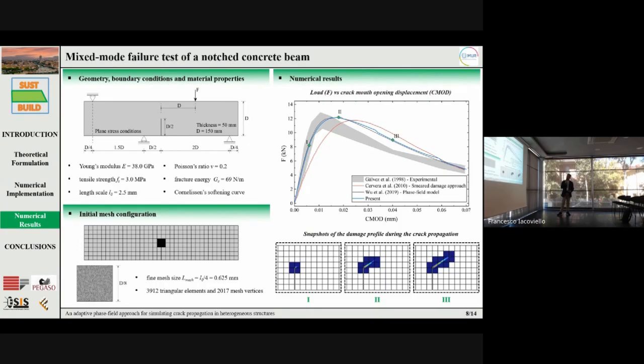The slide reports a comparison in terms of load versus crack mouth opening displacement between the present method, the experimental data, and the prediction provided by another numerical strategy. We can see that the obtained curves are in good agreement with the experimental data and the numerical results, thus denoting the reliability of the present method for predicting crack nucleation, propagation, and failure. In addition, we can see the snapshot of the damage profile during the 3 steps of the propagation.